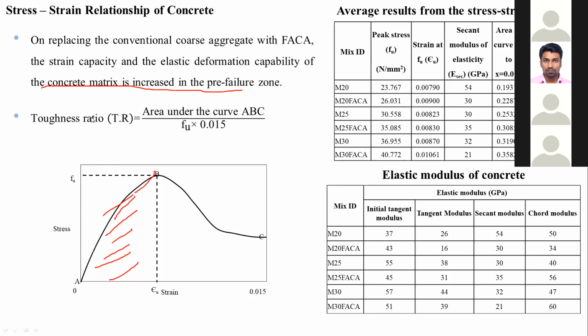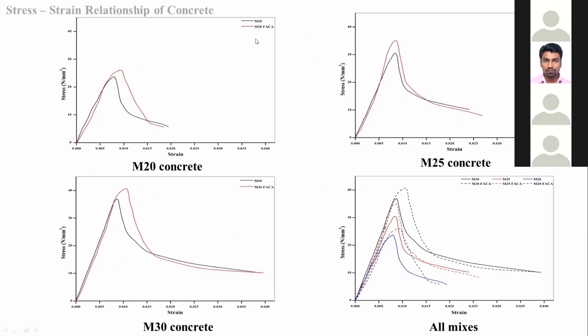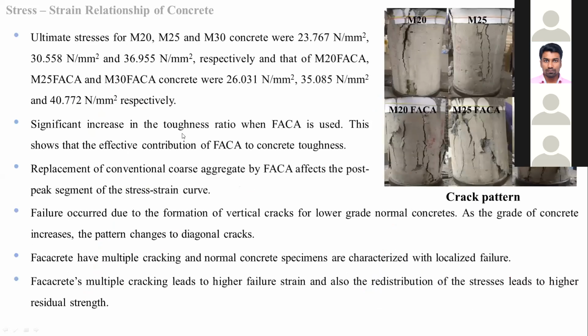From this graph, the red line is M20 FACA, and the black curve is conventional coarse aggregate. We can see that up to the pre-failure zone, the toughness ratio increases, and the strain also increases. As explained before, we can find a significant increase in toughness ratio when FACA is used. The post peak segment of the stress strain curve is also affected by introducing FACA into the concrete.